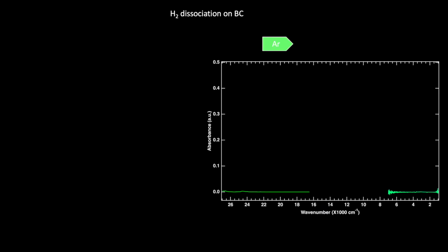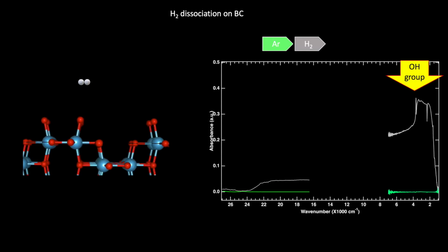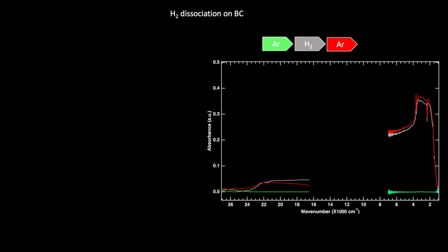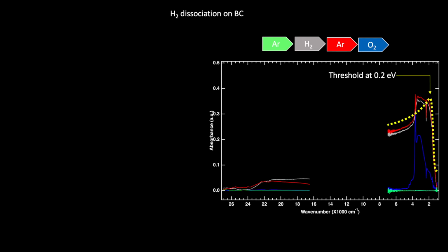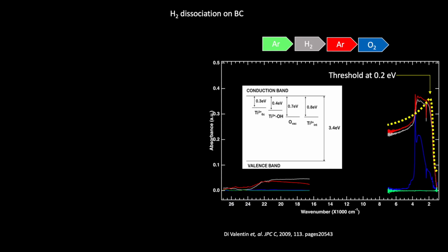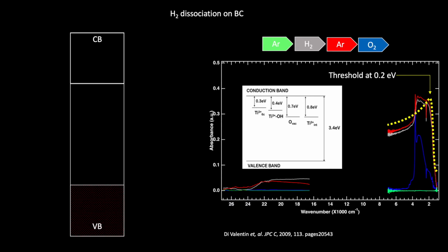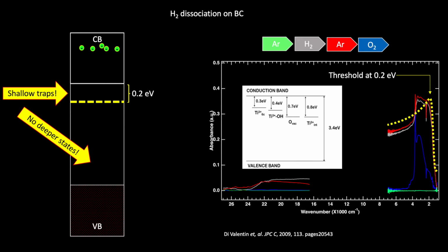We observed appearance of hydroxyl groups and development of broad electronic absorbance under hydrogen for our homemade pure anatase. The electronic feature was stable under inert argon, but oxidizing the surface removed the accumulated electrons very quickly. In this case, we observed a step-like electronic absorbance with the threshold at about 0.2 eV. This is comparable with de Valentin's report that lattice defects could create electronic states 0.3 eV below the conduction band minimum. Here, the shape of the electronic absorbance suggests that electrons are populating these shallow traps, and IR photons with energy higher than 0.2 eV could excite them into the conduction band. Absence of any significant absorbance in UV visible region suggests that there are no deeper electron traps in the band gap.